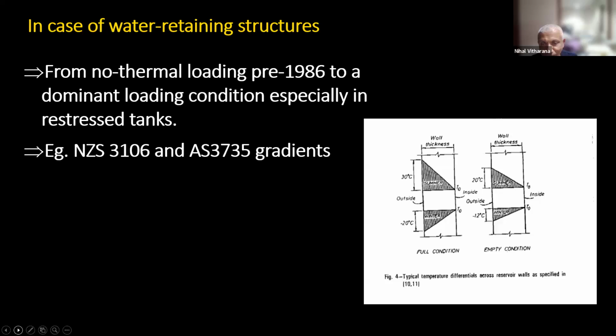Now, just to get our minds in order, if I look at 30 degrees centigrade and restrain a concrete member from expanding, with a Young's modulus of say 30,000 MPa, that is equal to 9 MPa compression, or tension on the other side. If we are designing a pre-stressed tank, it is very difficult to satisfy that criterion. That's where smartness plays in, because pre-stressing becomes uneconomical after about 6 MPa. So these are the two gradients which we have given. As I said earlier, these are valid only for wall thicknesses less than 200 millimeters. Anything greater will become nonlinear, but the code doesn't provide any guidance. Designers have to do it themselves, and most designers pretend they didn't see that commentary or limitation in the standard. Let's go to the next one, please.